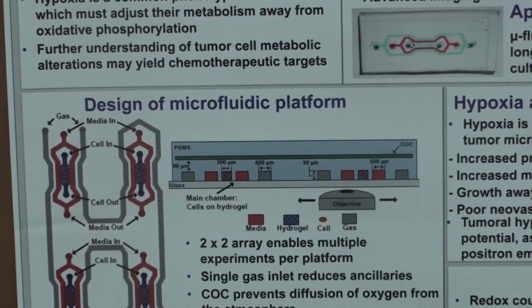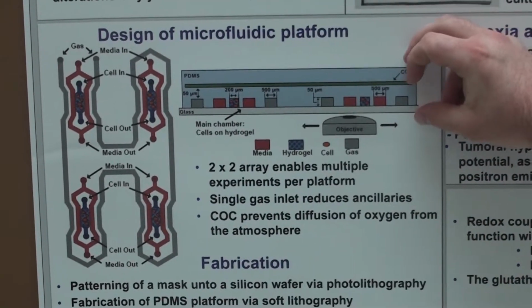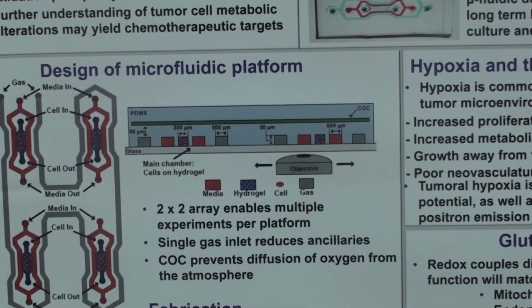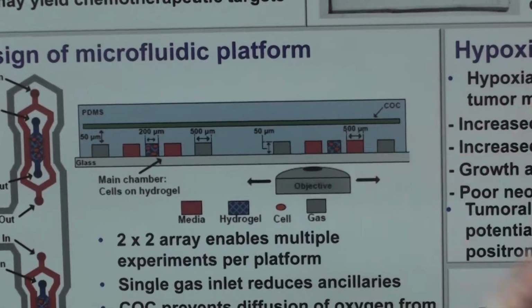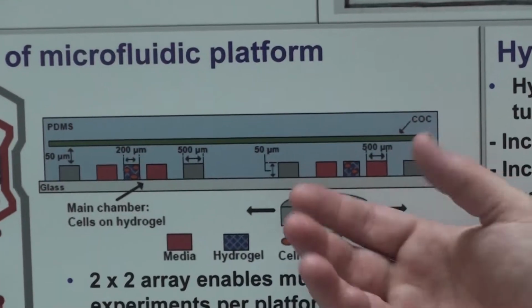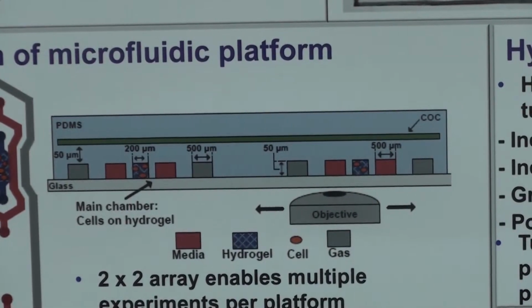Here, we've arrayed our device to allow for higher throughput work. It's a simple PDMS microfluidic platform, oxygen plasma bonded to a glass substrate that can be imaged directly because it's made to fit onto a scope.